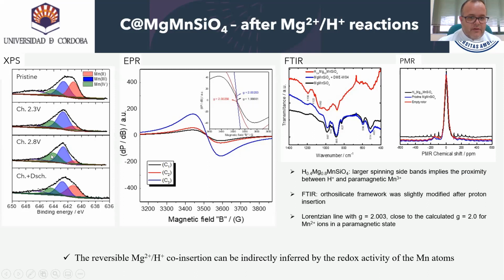After a complete cycle, the relative contribution of manganese 2 reaches the original value of the original sample. Thus, the reversibility of magnesium-proton co-insertion into the carbon-coated magnesium manganese silicate sample can be indirectly inferred by the redox activity of manganese atoms.